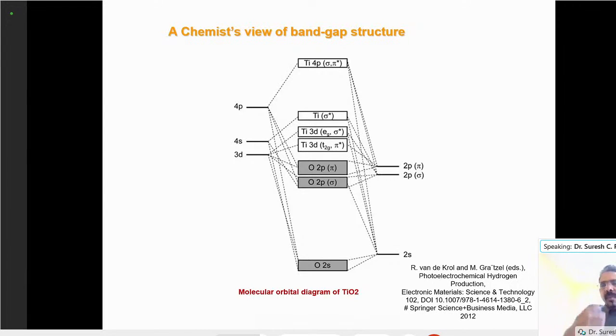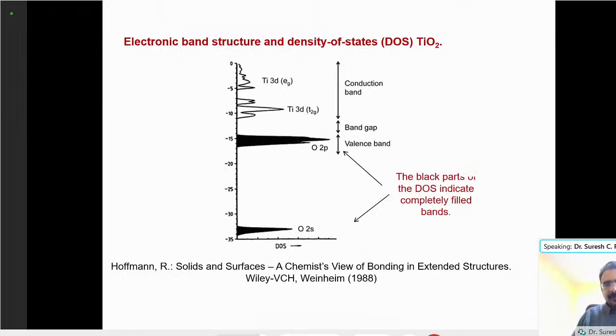So you need to do a lot of modeling work, simulation work. You need to work with your colleagues who are doing DFT studies, so they can calculate the energy levels. They can come up with solutions to identify which type of dopants we can use to fill the gap between the valence band and the conduction band. Quickly, I can say that the valence band of the titanium dioxide is made of O 2p levels, and the conduction band of Ti 3d levels. This information is very, very important to calculate the energy levels of the materials you have to fill between the valence band and the conduction band, so that the energy gap can be further reduced.